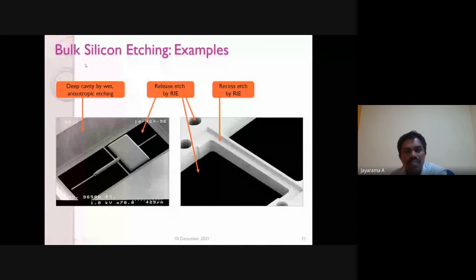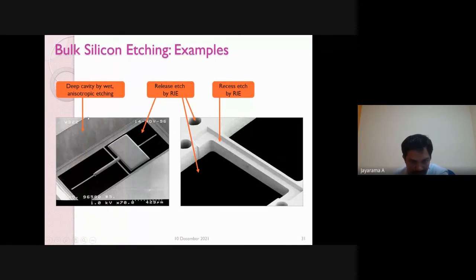This is bulk silicon etching, these are some examples - this is not our result. This is dry etching: release etch by RIE, reactive ion etching, and recess etch by reactive ion etching. You can make out the structure - it is very precise, clear structure. This is observed through the FESEM.